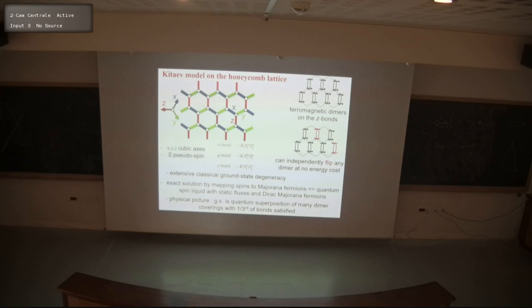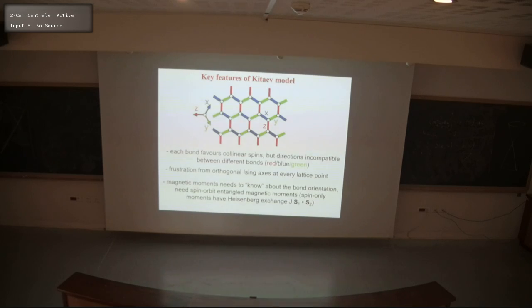And so fundamentally, the quantum spin liquid ground state is a large superposition of many dimer coverings, where each product state of dimers actually only satisfies a third of the bonds. Right? So the fundamental feature that gives rise to this extensive degeneracy is the fact that the Ising axes are incompatible when they meet at a point. So we have this quantum frustration associated with this incompatibility.